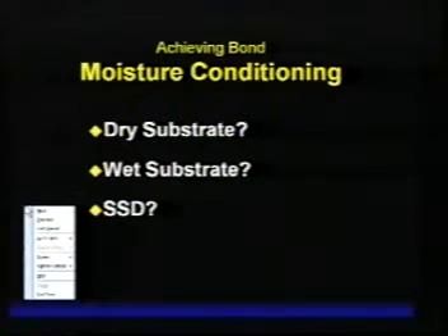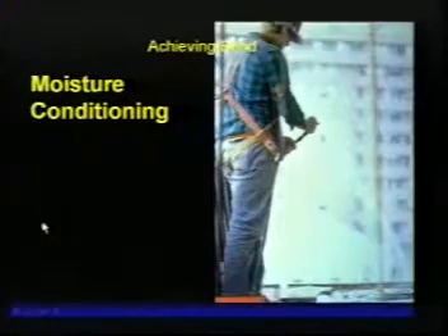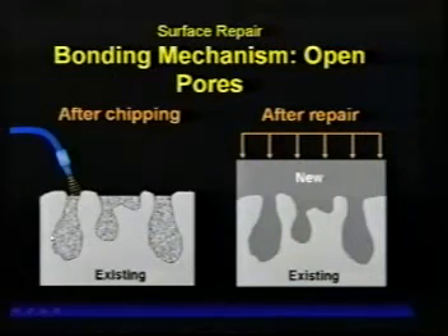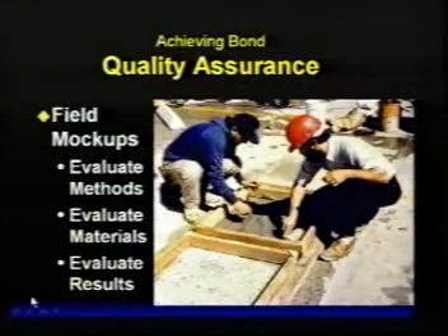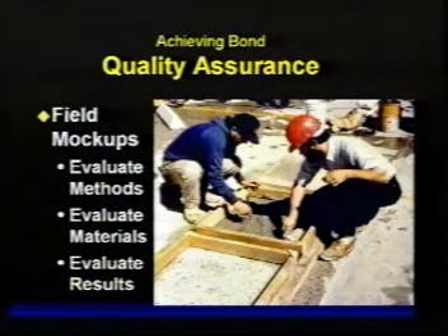And if we go back to the issue of the pore structure of the concrete, if this pore structure is too saturated, has too much water in it, it will actually reduce the bond. So it's recommended that you really pay attention to this particular aspect of moisture conditioning. Sometimes we overdo it and actually reduce the bond strength by filling up the pores too much with water. We recommend that a mock-up be performed with all three of these techniques to demonstrate the preparation, the moisture conditioning, whether a bonding agent is used or not used, and then the placement technique. And then these results can be evaluated and modifications to the procedures can be determined from there.